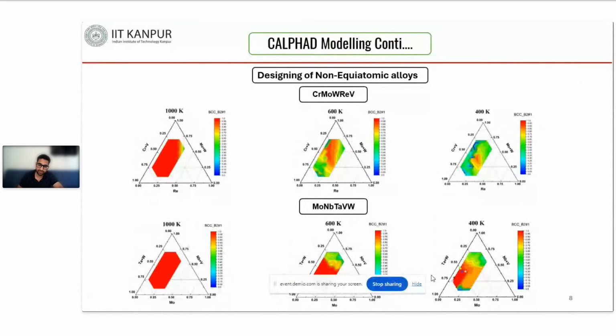So these alloys which show a single phase structure at 400 Kelvin are showing a single phase for the whole temperature range from 400 Kelvin to the melting point. So we got some alloys which show a single phase structure over a large temperature range.